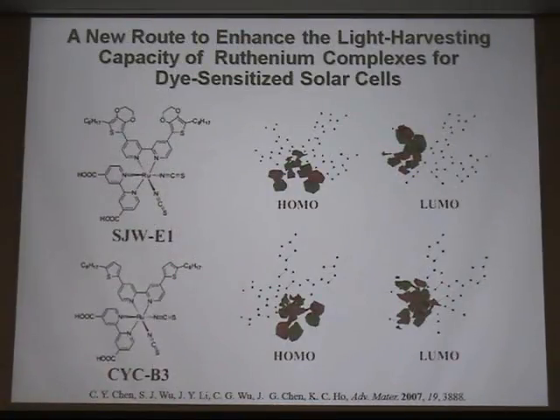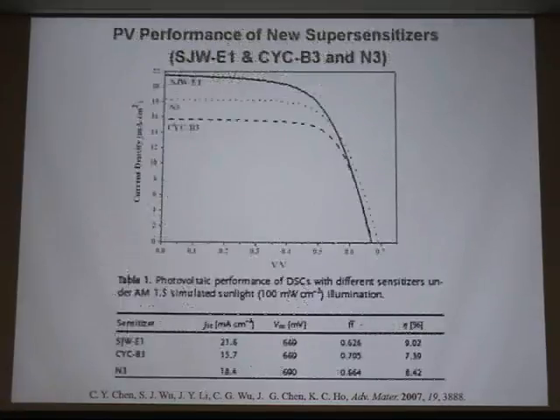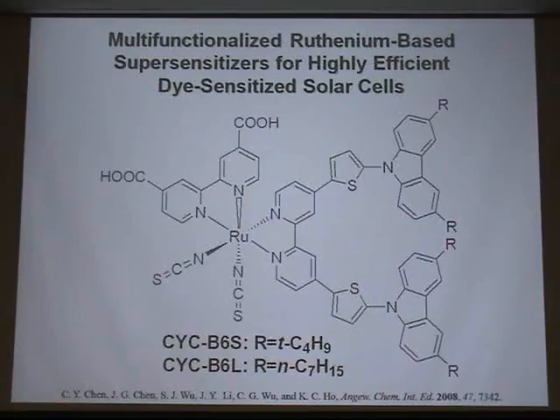Another dye, which is SJW-E1, we synthesized, also has the advantage of competing with N3. Here, N3 is around 8.42 and SJW-E1 gets 9% or so. Again, our dye has a longer electron lifetime.